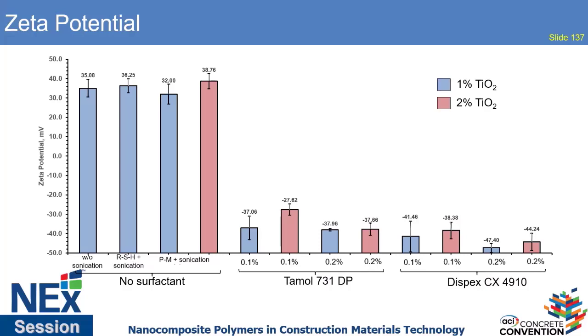If you take a look at the first sample without sonication, we saw in the pictures that this sample is not stable because there was a lot of sedimentation. However, we still get a zeta potential of 35. So really, when we are talking about the stability of those materials, it's an overall thing.